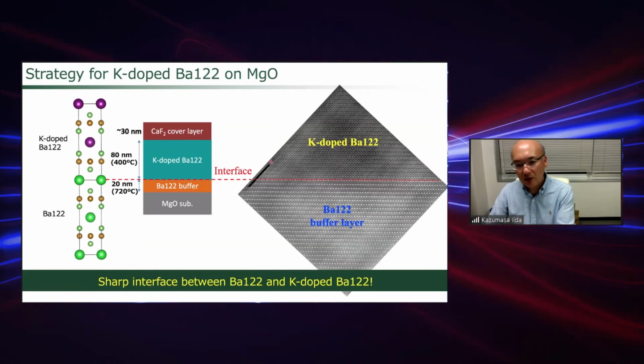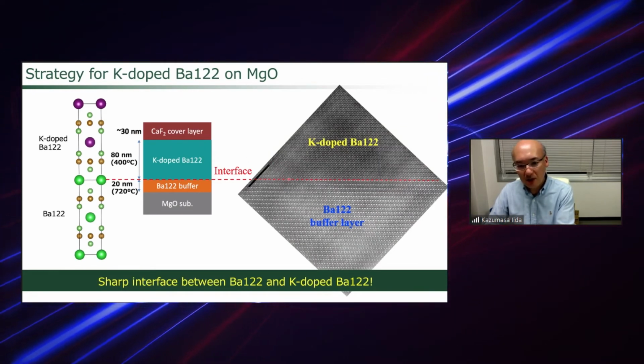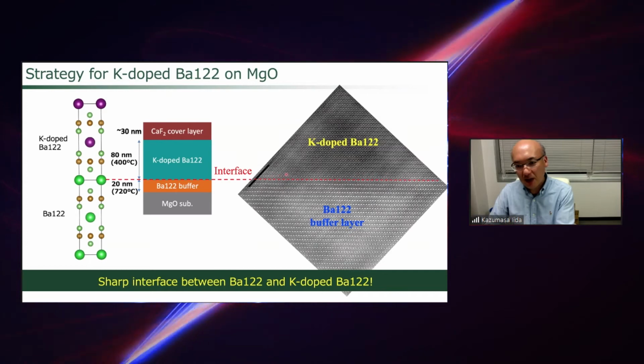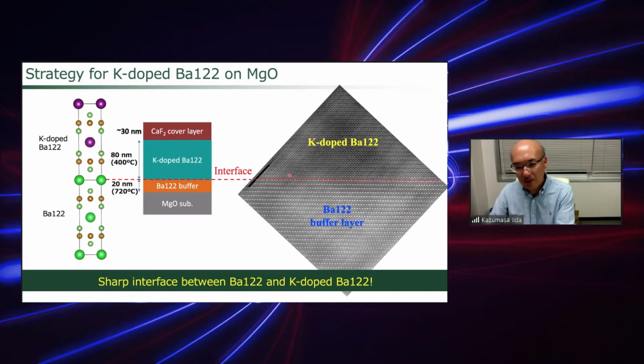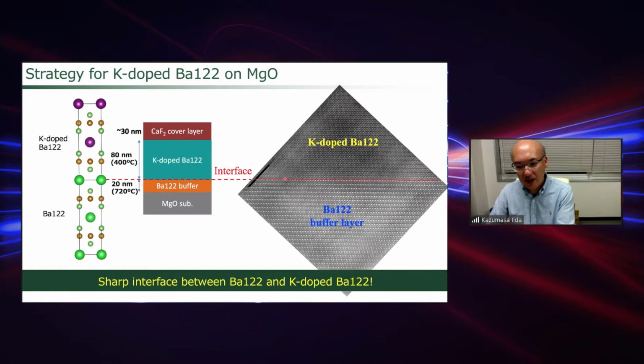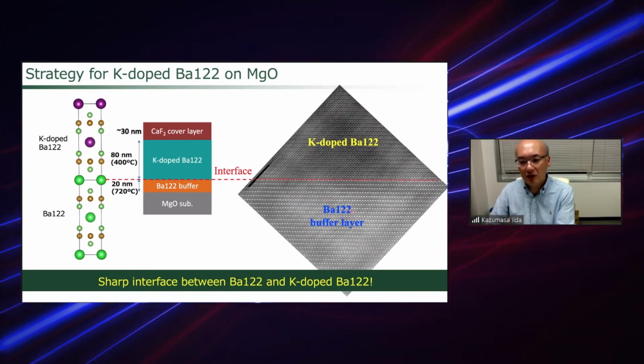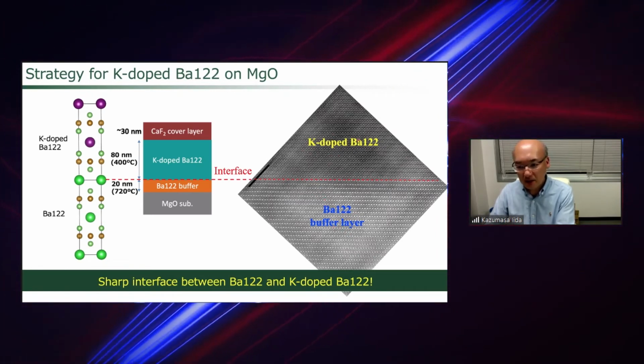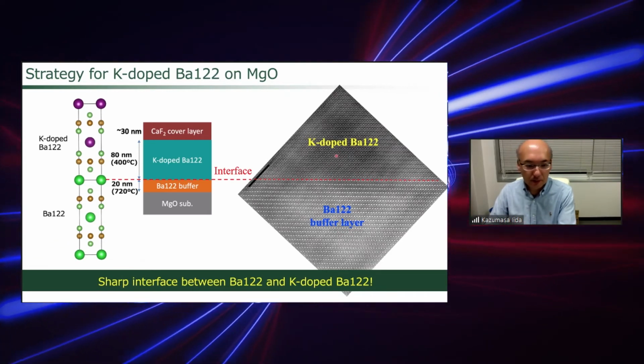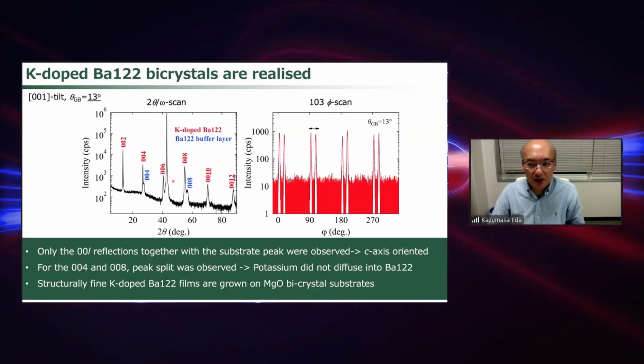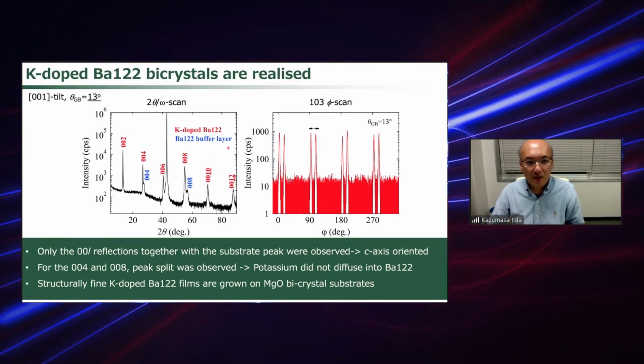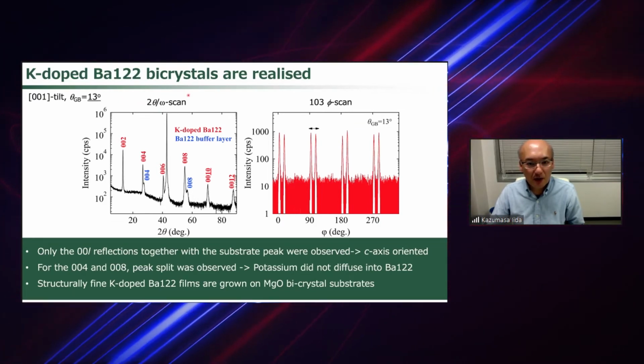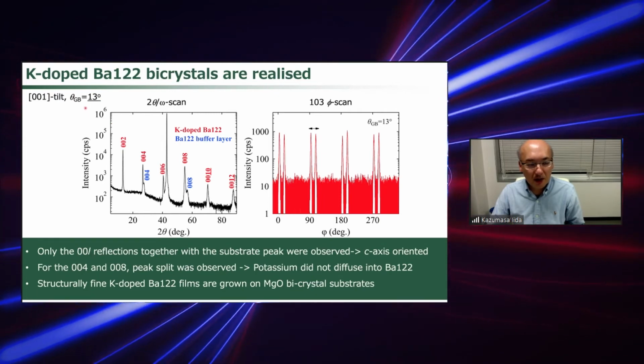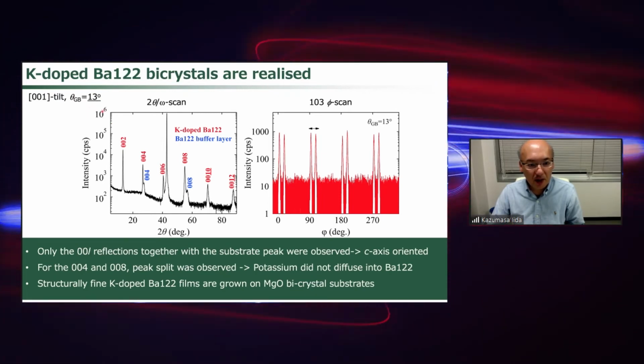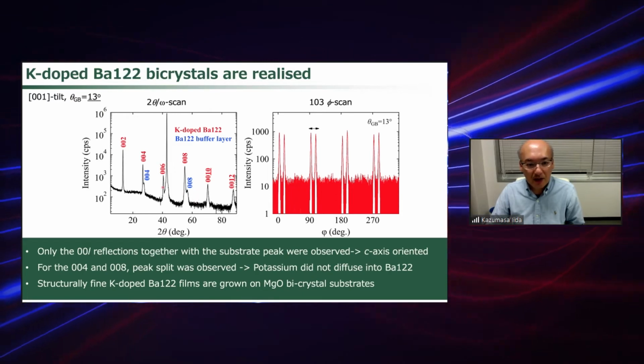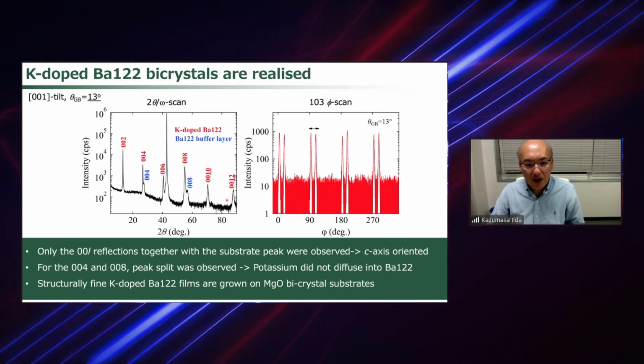So here is a cross-section TEM image of this bilayer structure. And as expected, we obtained a very nice sharp interface between the barium 122 buffer layer and the potassium-doped barium 122. And here is the structure characterization of potassium-doped barium 122 bicrystals having a grain boundary angle of 13 degrees. And you see that very nice c-axis texture is observed.